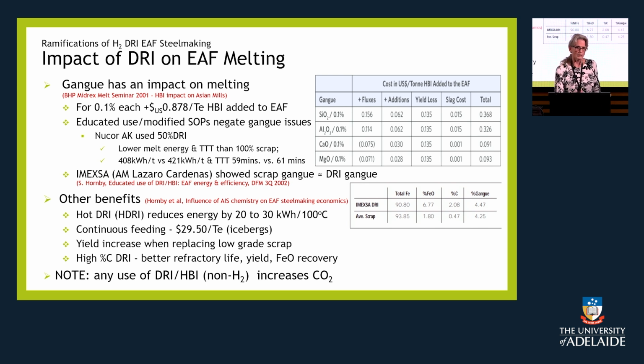IMEXSA, just as a side, showed that there was actually quite a lot of gangue in a scrap charge, and I'll show you how that can be beneficiated a bit later. So that's 4.25% in scrap. Other benefits from DRI come from charging it hot, where you can get 20 to 30 kilowatt hours per 100 degrees C drop in kilowatt hours.